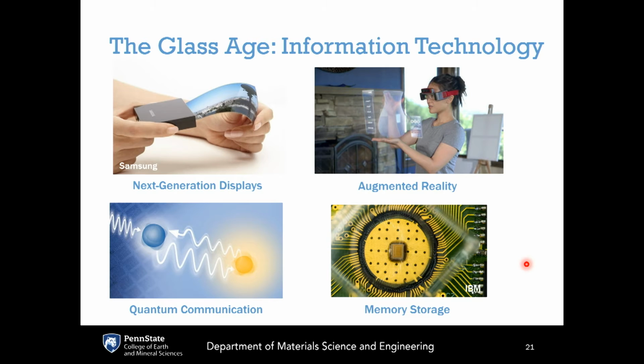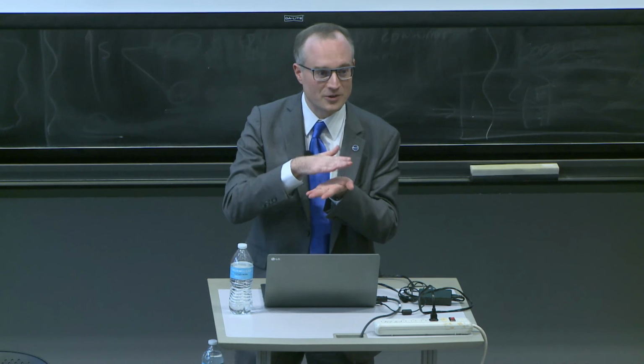So what's next? Looking forward, we know that glass has brought us to this information age, but there's more to come. If you look at some of the new phones that are coming out, for example, from Samsung, with foldable displays, flexible displays, these are being made possible by ultra-thin glass, 100 microns or less. We think of glass as being a rigid material, but if you lower the thickness down to under 100 microns, it becomes flexible. The thinner you make it, the more flexible it becomes. And so these companies are starting to build displays based on this ultra-thin, flexible glass.